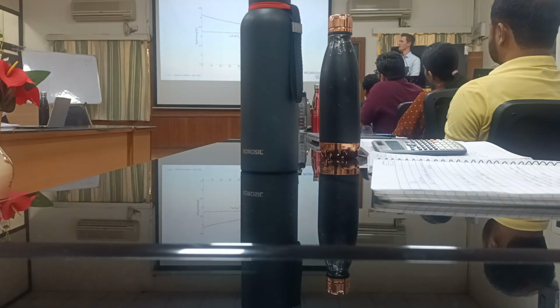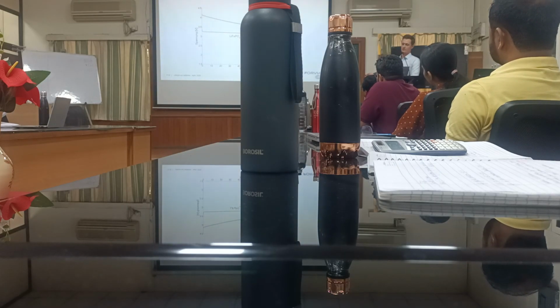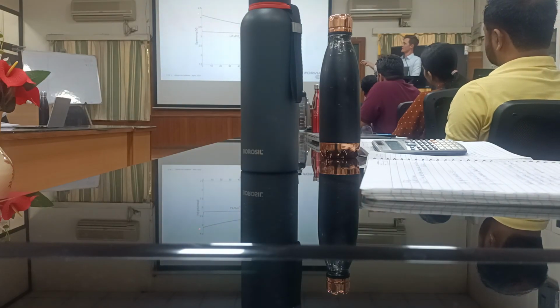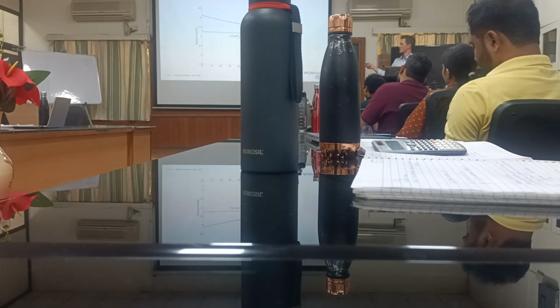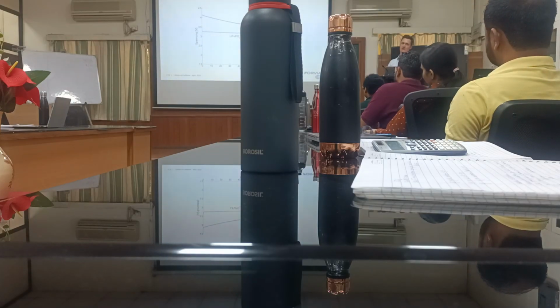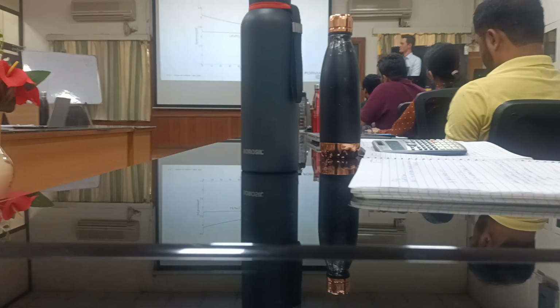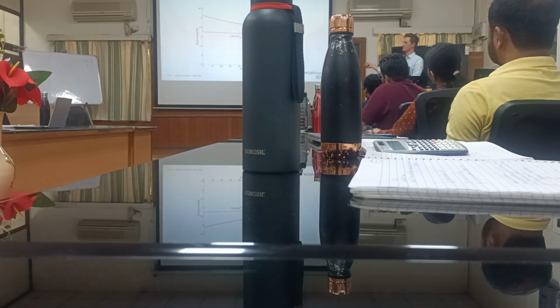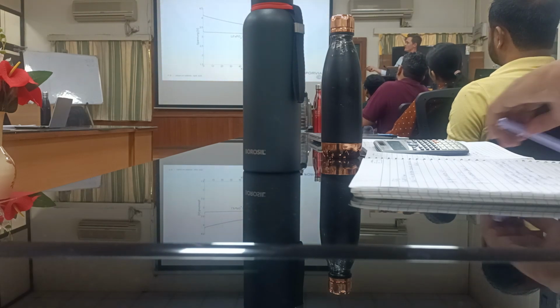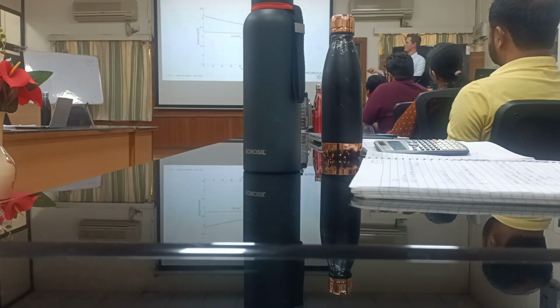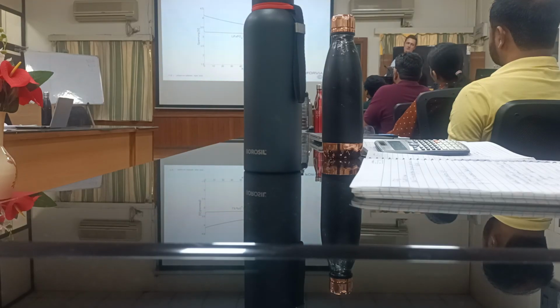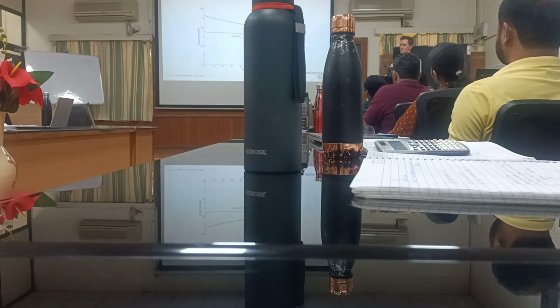Sticking with open circuit voltages, the one of NMC looks like this, we have just seen it, coming from 4.2 something to just below 3, usually it's 2.6, but the cells are often not used down to the lowest voltage point. However, what I want to show, LFP, which is the second most popular battery material, the open circuit voltage looks like this. So from battery cell capacity 0 to 100%, you have almost no voltage change, at least in a certain region, maybe up to 80%.